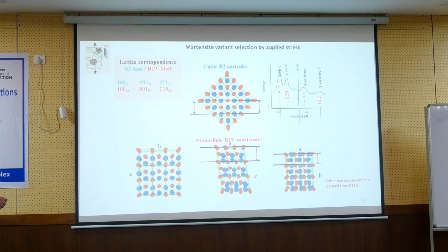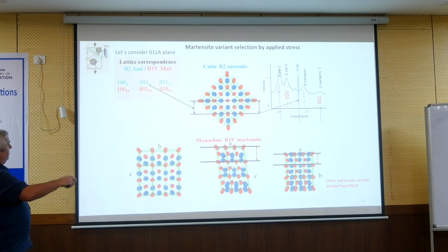So what does it show? You have austenite, and this is the 011 austenite plane over here. It has some lattice spacing. This is a very important plane in the crystallography of transformation. I will talk more about it. If you do the experiment, because of the Bragg equation, this lattice spacing will give you the peak around this position. You see there is almost nothing because this pattern is mainly martensitic, but there is some remaining austenite.